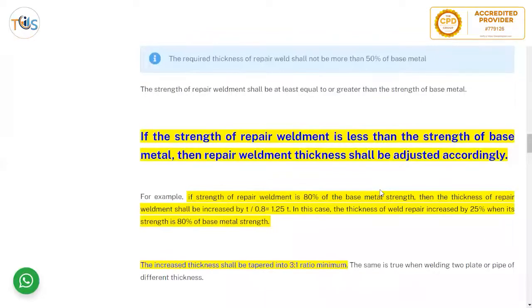The required thickness of repair weld shall not be more than 50% of base metal. So if you're grinding off some defects and then building up by weldment, the depth should not be more than 50% of the base metal. The strength of repair weldment should be at least equal to or greater than the strength of the base metal. So always the weld strength should be greater than the base metal, because due to the weld you already have some stress concentration here, because there is a change of shape and also the ripples on the weld. And if it is less than the strength of the base metal, the repair weld thickness shall be adjusted accordingly.